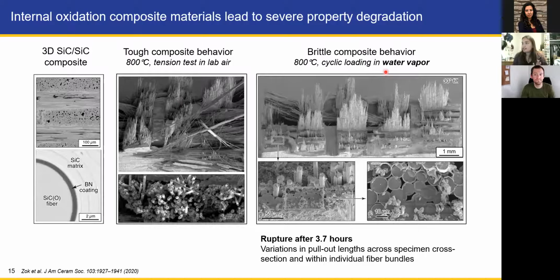But when we expose these materials to water vapor environments to try to simulate the exhaust gas, we get some complex behavior. So some of these fibers show brittle failure, where we have very flat fracture surfaces, like you can see here. Some of them seem to be unaffected by the water vapor and have tough behavior. And this one was exposed to cyclic loading. So you pull and release the load, and it failed just under 4 hours. And these materials really need to survive tens of thousands of hours in an engine environment. So we need to figure out what's happening.